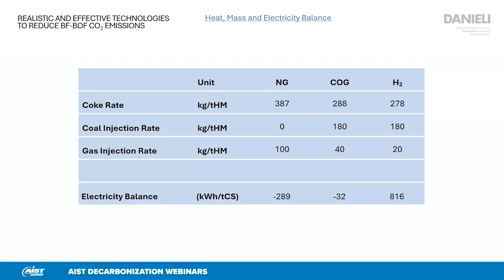And as you can see, the coke rate for injection of natural gas is relatively high because we have nullified coal injection rate in order to allow maximum usage of gas. The coke oven gas coke rate and hydrogen coke rate are less than our reference blast furnace, which means that CO2 emission reductions will be accomplished. And for your information, the reference blast furnace plant had a coke rate of 313 kilos.